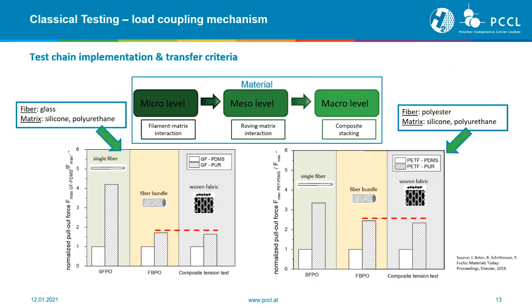And therefore, we also developed different test setups. Here, as an example, we developed the test chain starting from single fiber tests, for the characterization of single fibers, where we work together with some scientific partners. Then we developed here in Leoben a test setup to test fiber bundles. And finally, we've also implemented a test setup where we can directly test